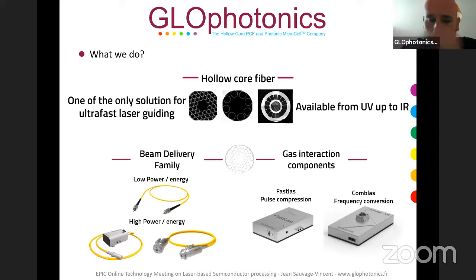And so we have developed different fibers in order to address different wavelengths from UV to infrared. Basically in the infrared, 1064 nanometers, 1032 nanometers, even in the green, 532, 515 nanometers. And we go down to UV, down to 355 nanometers, and also 266 nanometers. It's a different fiber. We have a different design for each fiber, but each fiber is available for this type of wavelength, a range of wavelengths.